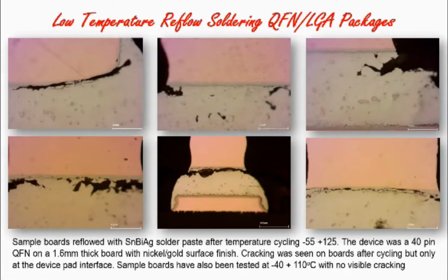But with temperature cycling with QFNs, with traditional SAC alloys, you might expect 1,000 to 2,000 temperature cycles, depending on the package size, the die size, and obviously the testing. What I'm showing you here is just some examples of some experiments that myself and Richard from the SMTA committee did, just to get a feel for what's actually happening and failures. You can see these are conducted on low temperature joints. Initially at -55 to +125, which is really outside of the window that you should be using. We repeated these tests at -40 to +110 with no visible signs of failure up to 1,000 cycles.